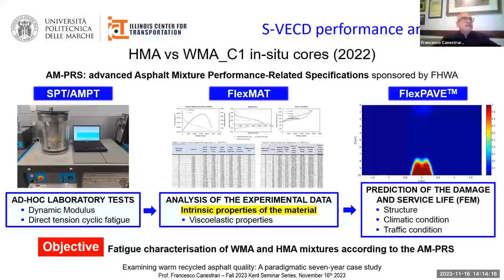Then we applied the simplified viscoelastic continuum damage analysis for the evaluation of performance based on in situ cores taken in 2022 from the trial section. First, we carried out the laboratory test with the asphalt mixture performance tester. Then we analyzed the experimental data with the FlexMAT tool to obtain the intrinsic properties of the materials. And finally, we predicted the service life of the pavement by using the FlexPAVE software.